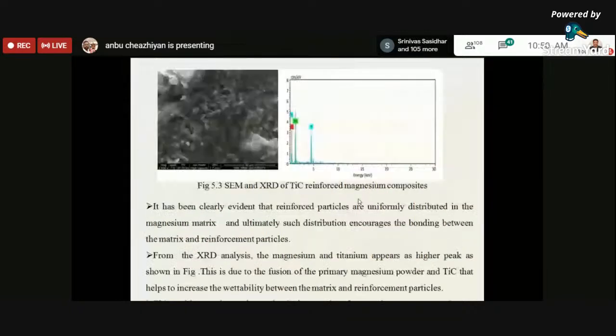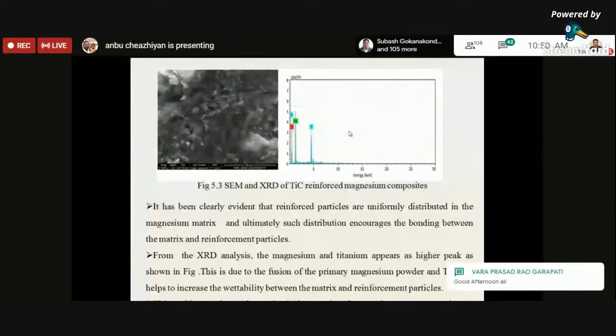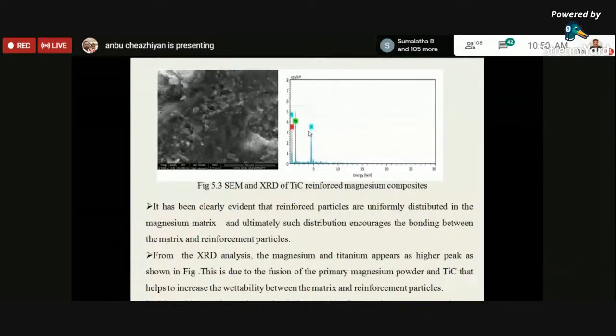So these are the SEM and XRD images. In the XRD images, it clearly shows that magnesium and titanium occupy the peaks, enhancing the mechanical properties. It is clearly evident that the reinforcement particles are uniformly distributed in the magnesium matrix, and ultimately such distribution encourages the bonding between the matrix and reinforcement. This is from the XRD analysis.